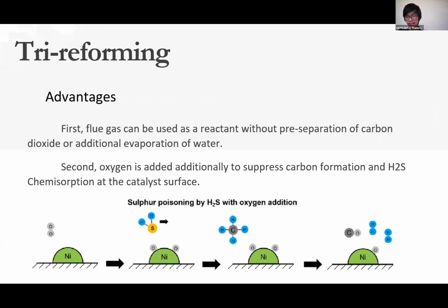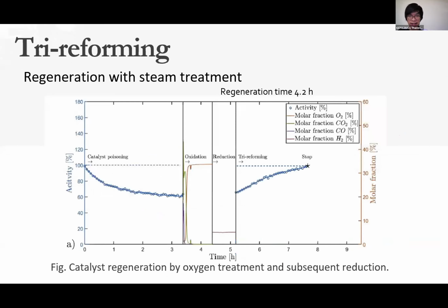The regeneration mode started with the injection of oxygen, which increased the carbon monoxide and carbon dioxide, referring to the carbon content and indicating combustion of coke deposit. After some minutes, the carbon deposit no longer produced any combustion product, and nickel was completely oxidized to nickel oxide. After the oxidation, the reactor was filled with hydrogen and nitrogen to reduce nickel oxide to pure nickel.